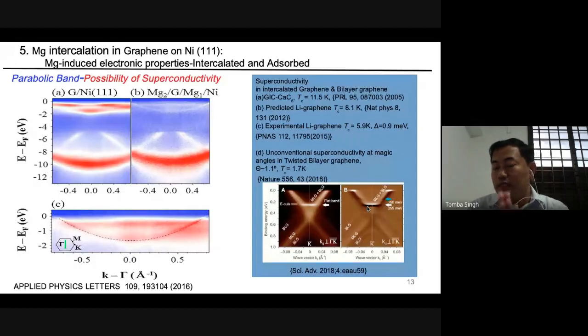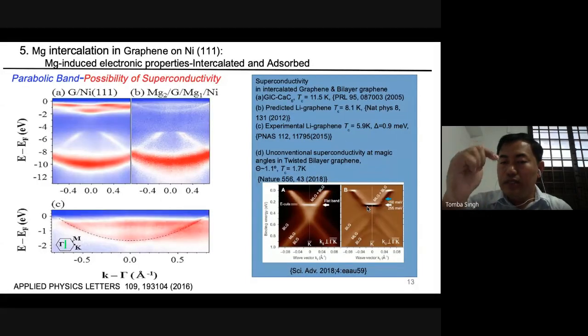What I'd like to mention is that the moiré pattern is very important because it can produce a potential, and it can be added to the graphene band structure, so the graphene electronic property can be modified. I'll come to the moiré pattern in the coming slides. The signature of superconductivity in the band structure is the flat band. In the case of GICs, the parabolic band at the gamma point, from the graphene valence band or the interlayer bands, is visible in the band structure. They are the signature of superconductivity. So coming to our result, in this system, magnesium adsorbed on graphene and magnesium intercalated in graphene on nickel, we observe a parabolic band just below the Fermi level at the gamma point.